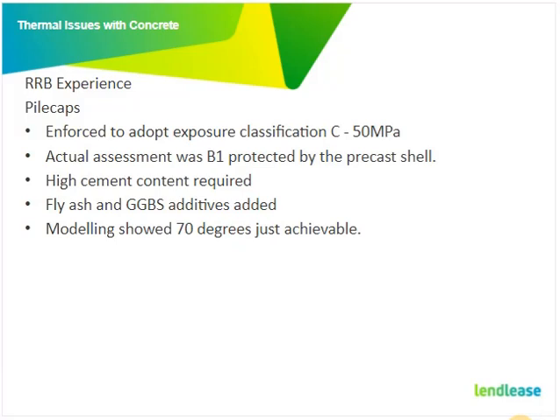Yeah, so on the pile caps, we were forced to use exposure classification C. The actual assessment was B1. Once you did the assessment of the actual concrete on the inside, the shell was C. That's fine, it was easy enough to do in the precast yard, but with that big thick concrete pour, it was actually B1. It's fully protected. There should have been no reason why we shouldn't have been able to use it, but we used Class C.